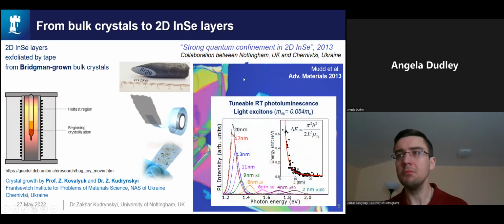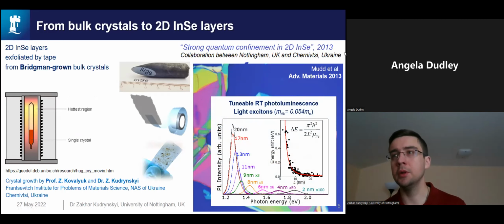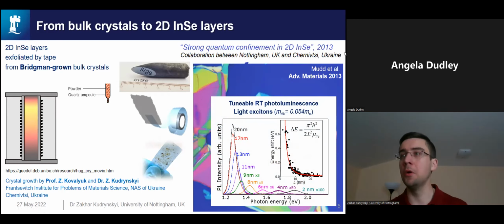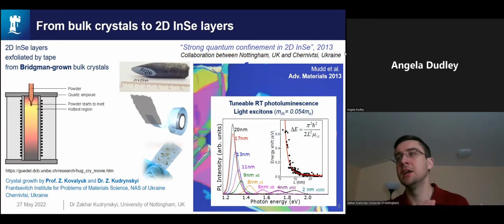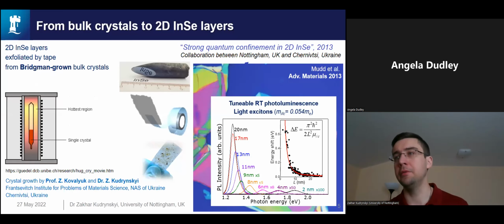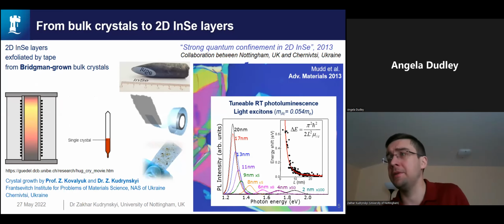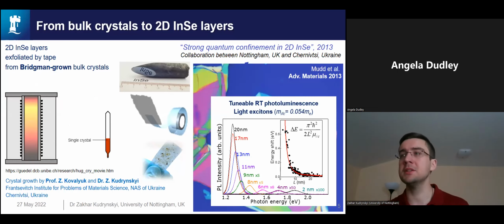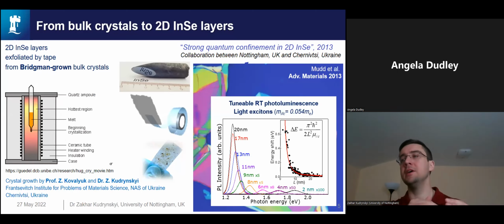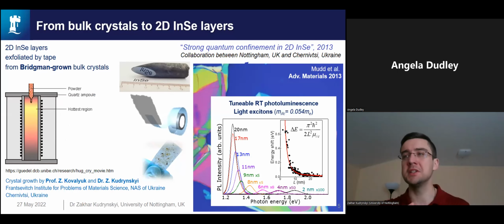And what we observed is that in this material, the optical gap strongly depends on the layer thickness, as we go from relatively thick flakes of about 20 nanometers to just few layers. We studied hundreds of flakes of different thickness and found a strong energy shift with layer thickness that can be reproduced by a simple effective mass quantum well model. In this crystal, the effective electron mass is so light that when we exfoliate this material down to thinner and thinner layers, the zero point energy of the electrons increases, and this increases the band gap, which is shown here.